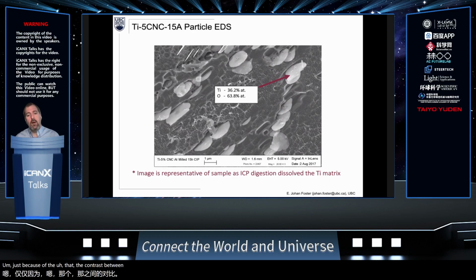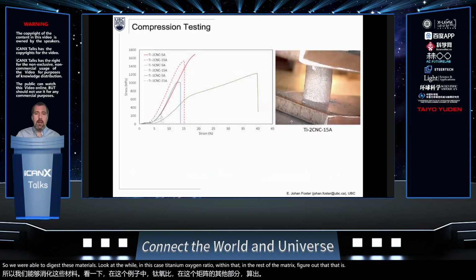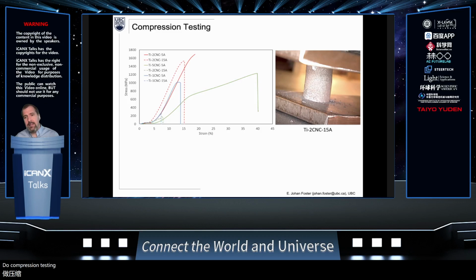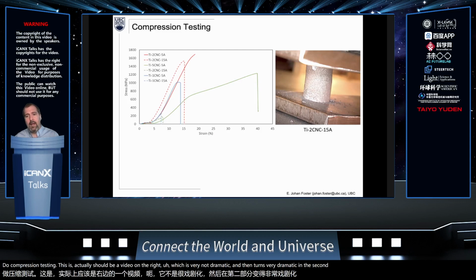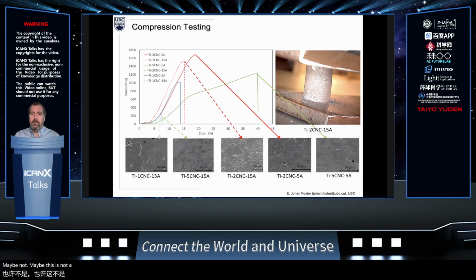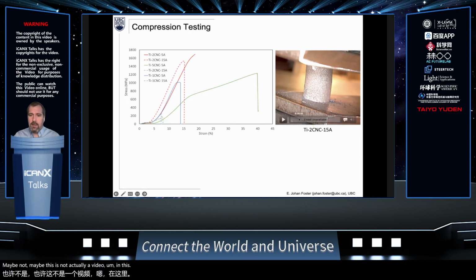Okay, so we were able to digest these materials, look at, in this case, the titanium oxygen ratio within that and the rest of the matrix, and figure out that that is titanium oxide. Do compression testing. This should be a video on the right, which is not dramatic and then turns very dramatic in a second. Hopefully. Maybe this is not actually a video. In this case, it really should be. Nope. Of course, it's not playing.